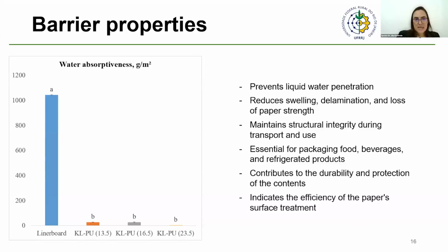And we performed the Cobb test. We performed it in 30 minutes, and we have an increase of the water barrier by applying the coating on the paper. The values reached a lowest of 6 grams per square meter. This ensures resistance to humid environments and protection against liquid penetration, which is important for transport and use of the packaging and the products inside it. So this property, water absorption, like water vapor transmission, ensures the packaging durability and protection of its content.